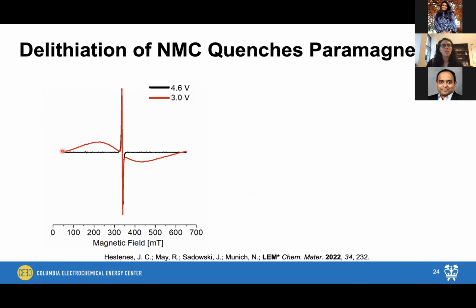And then we also have our black spectrum here. This comes from the composite in the charge state. So we charge these batteries to 4.6 volts. And then what we notice is that all of the signal from the NMC particles is completely quenched. So we don't actually have any EPR signal. We know that we still have manganese 4+ in there, but we don't actually have any exchange coupling with any more paramagnetic centers in the active particle. So basically the system is just so dilute that we don't actually get any signal anymore. Of course, we still have some signal from our conductive carbon. That's the sharp signal in the center. But all of the signal from the NMC811 has gone away after we charge the battery.